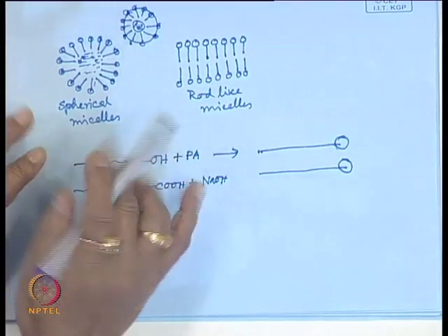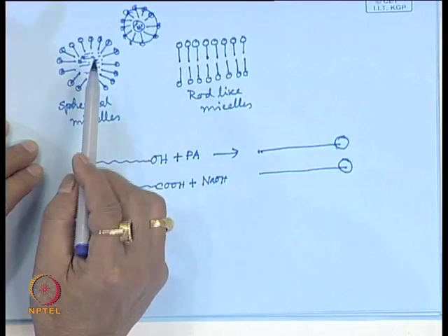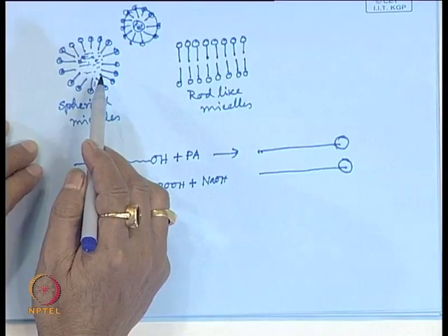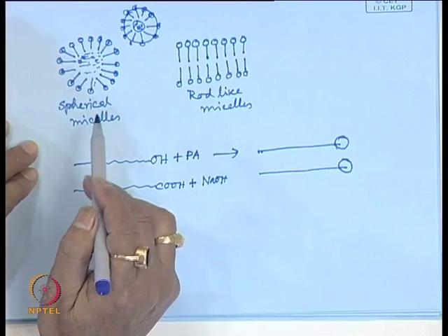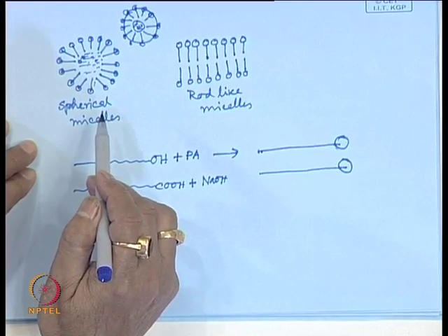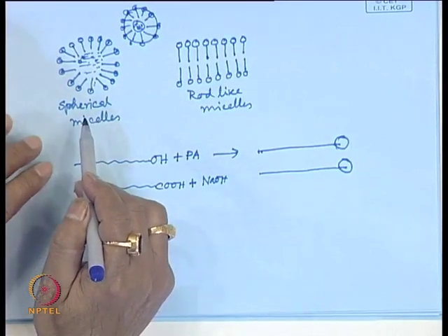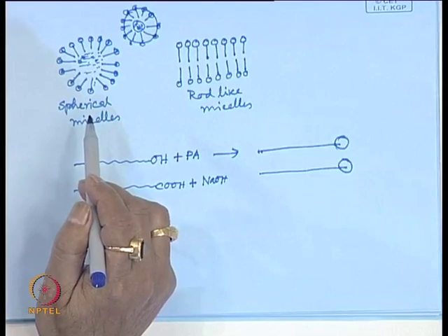Now, you want to polymerize this monomer trapped inside this micelle. For this we need an initiator molecule. In case of suspension polymerization, we deliberately added some initiator like benzoyl peroxide, azobisisobutyronitrile, or cumene hydroperoxide or dicumyl peroxide. Those get soluble in the monomer phase in suspension polymerization. So, there the suspended monomer droplet is converted to a polymer particle.